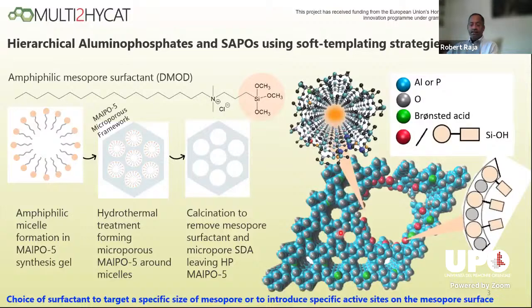So in this case, here is a typical micropore of an aluminophosphate moiety. The pore aperture here is about 7.3 angstrom. And if one wants to enhance mass transport and diffusion through this soft templating approach, we have introduced this mesopore here, which is about 30 to 40 angstrom diameter. So this is very similar to your mesoporous MCM-41 silica type materials, which have these pendant silanol groups which line the internal walls and cavities of the pore.